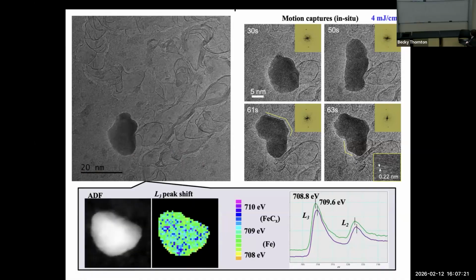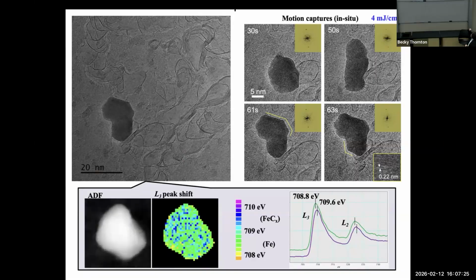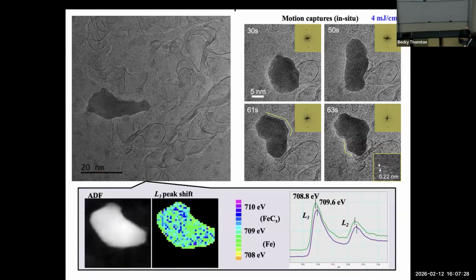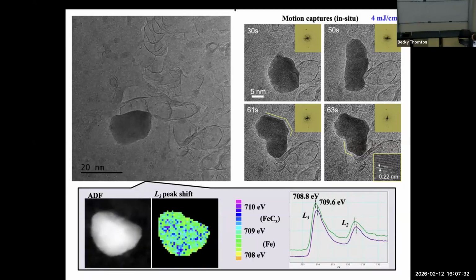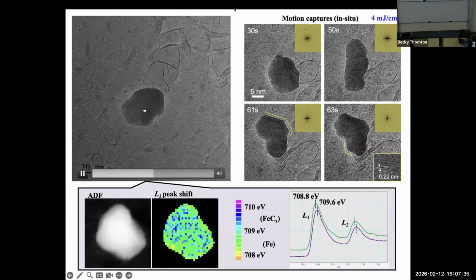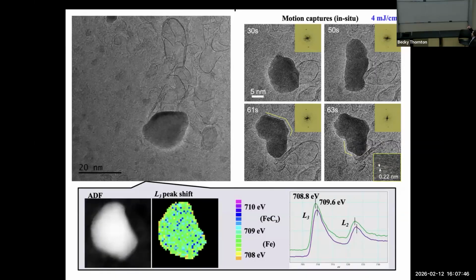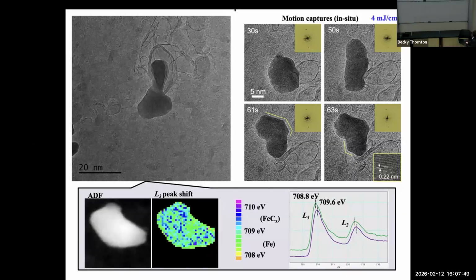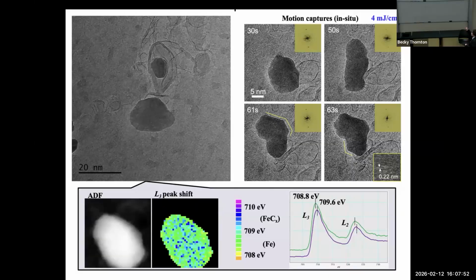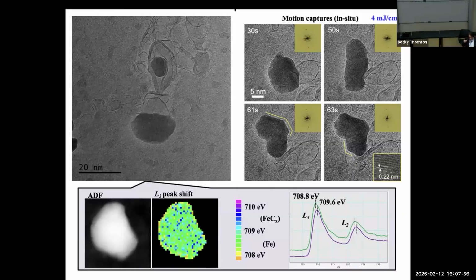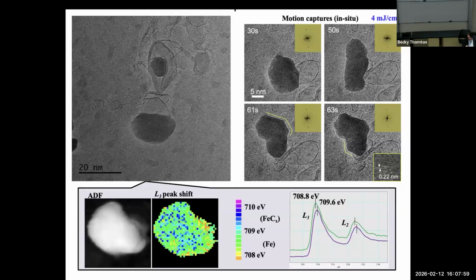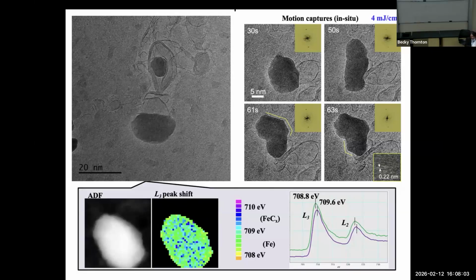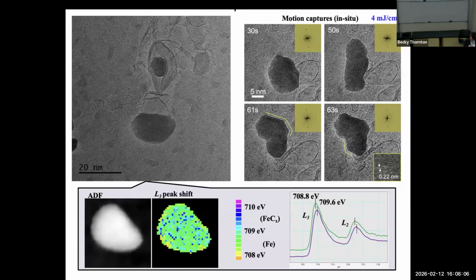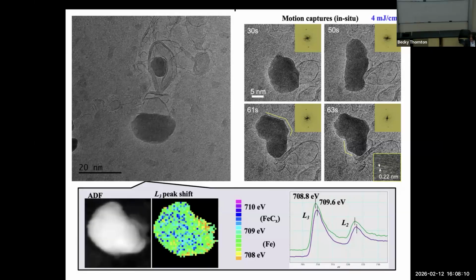This is a kind of in situ microscopy where the iron particles can act as a catalyst to grow graphite layers. As you can see, these iron particles are moving and they are making some carbon layers outside. So these iron particles eat carbon atoms and they make the graphite afterwards. This is the in situ growth of carbon nanostructures, but we can make some in situ EELS chemical map, EELS high resolution map, to get information from the iron particles. Okay, I'm coming back to this point later.